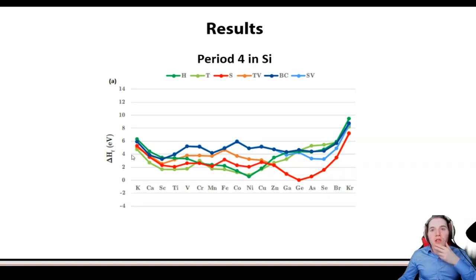You see that the curve is actually quite boring and smooth. All of these are pretty much flat. And in this region here, you see that it's almost a straight line. It's not really a straight line, but if you would just simulate 2 points here and pull a line through it, your errors aren't going to be that big. That shows you already that with simple machine learning, you can probably predict what this will look like even from a few points.